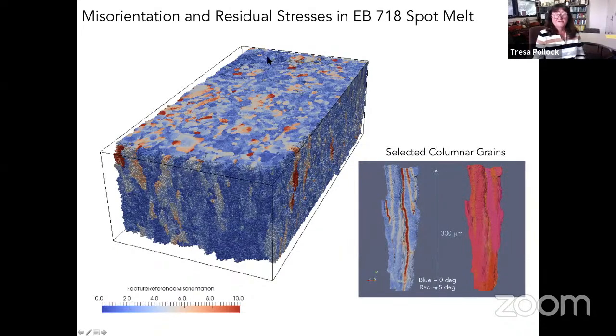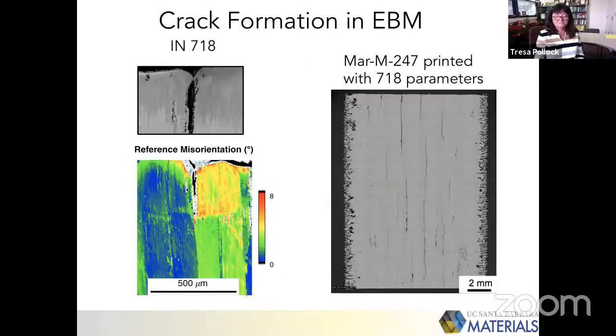But the important point is that these misorientations are not uniformly distributed in the structure, and that if one tracks individual grains as they solidify, there is some tendency for the misorientation to build up in the regions where we have the final solidification event. And so again, controlling the gradients and velocities strongly influences that.